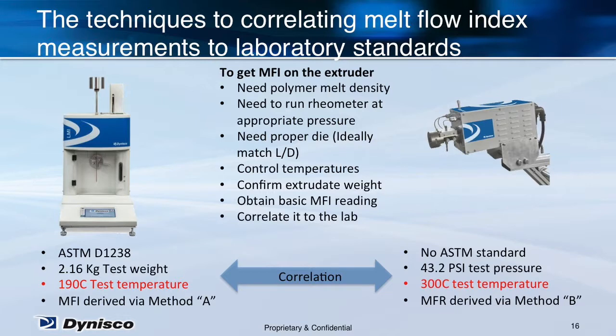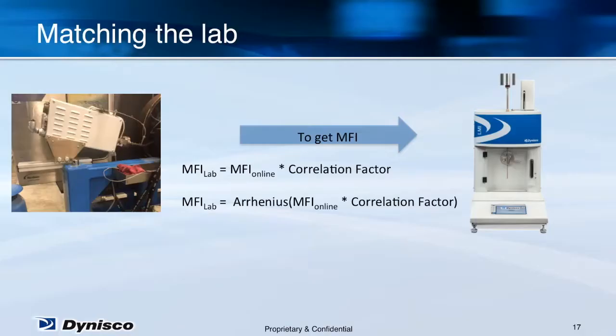After you know your machine is good, and the material is good as well, the next thing to talk about is the fact that you're not running your production process at the melt flow index test temperature recommended by the ASTM standard, and melt flow index is a function of temperature. So the issue we have identified is that in real life, you aren't processing your polymer at the temperature the melt flow index testing is done at.